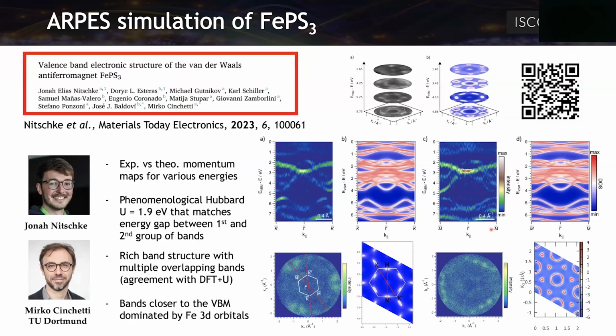Also, in collaboration with the group of Mirko Cinchetti, we were simulating the ARPES. In this case, we compared the experiment with the theory. The Hubbard-U that we are matching is very similar to the one that we obtained in the previous work, so 1.9, 2.2 was in that range. And this was fitting this gap between these two electronic states here in the ARPES experiment. And here we have the calculation. So this is reproducing very well the different curves. So this is an ARPES simulation.